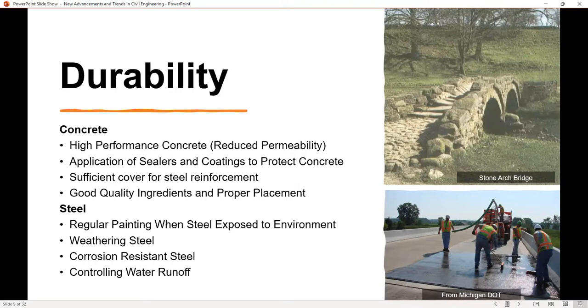One is to use what we call high performance concrete, which essentially reduces permeability. A major way that concrete is harmed in the long term is when water mixed with harmful chemicals like chlorides and sulfates gets into the concrete, and if there are embedded steel reinforcing bars, it causes corrosion of the steel, and when the corrosion happens, the steel wants to expand. As it expands, it pushes the concrete away, cracks it, and leads to spalling.